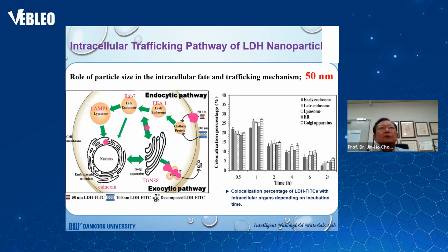In case of 50 nanometer particles, they were almost equally localized in the lysosomes, as you can see here in the right-hand side, and equally localized in lysosome and the Golgi apparatus during 30 minutes to 6 hours, suggesting that they follow two different pathways with the same degree. One is the typical endocytic pathway represented by the early endosome, late endosome, lysosome. And the other is the exocytic pathway represented by early endosome, Golgi.